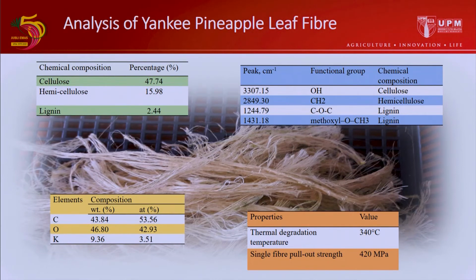These are the properties of pineapple leaf from the Yankee pineapple variant. The chemical analysis, through the Technical Association of the Pulp and Paper Industry, TAPPI, shows the presence of cellulose, hemicellulose, and lignin. The chemical composition for cellulose, hemicellulose, and lignin is 47.74%, 15.98%, and 2.44% respectively. The elemental composition of the fiber was analyzed by energy dispersive X-ray spectroscopy, EDX.